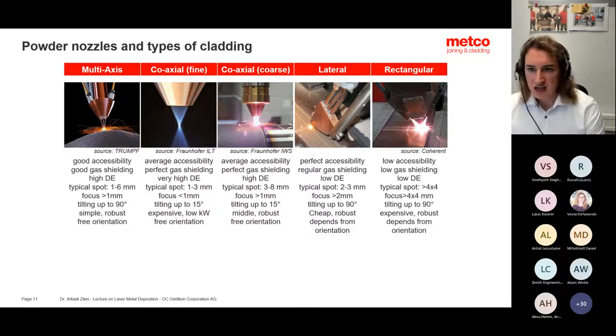What does high deposition efficiency mean? That we work with 90 plus percent of powder consumption going directly into your coating or component. And we have really low waste of powder material, which was always advantageous. What you see on this slide is more or less how it was, for example, 10 years ago.